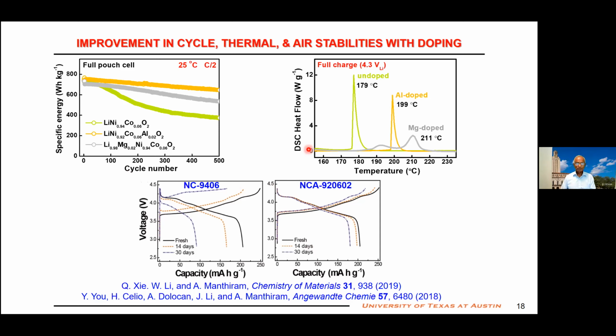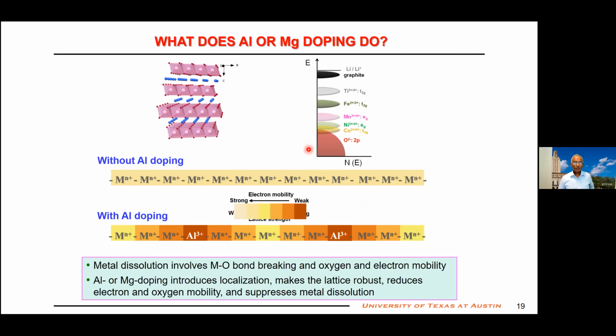Amazing example. I used to work with superconductivity in the late 80s, copper oxides with Professor Goodenough, as a postdoc after moving to UT Austin. I know we try to increase the Tc, then something else will happen. So now, what is so magic about aluminum or magnesium or other dopants? The structure has edge-shared octahedra. These transition metals see each other, even though their energy levels are a little bit different. They can very easily hop, or the electron density is very much delocalized in these oxides. The structure allows that. You see the beauty of the structure.